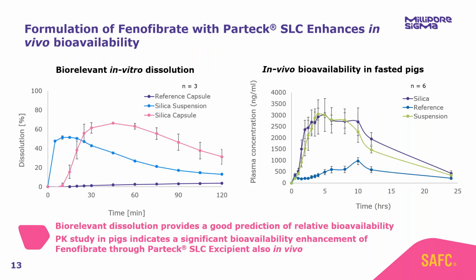So what did we see from the data? On the left-hand side, we have our biorelevant in vitro dissolution. This was conducted in FaSSIF. The suspension is in blue, the capsule is in pink, and the crystalline fenofibrate is in purple. And what you can see is that both the suspension and the capsule significantly outperformed the crystalline fenofibrate. And if we look to the right-hand side of the screen to our PK curve, you can see that both of these formulations significantly outperformed the crystalline molecule. In green and in purple, we have the AUC, the exposure curves of both of these formulations. And you can see that the bioavailability of fenofibrate in this instance was much higher than the crystalline fenofibrate.